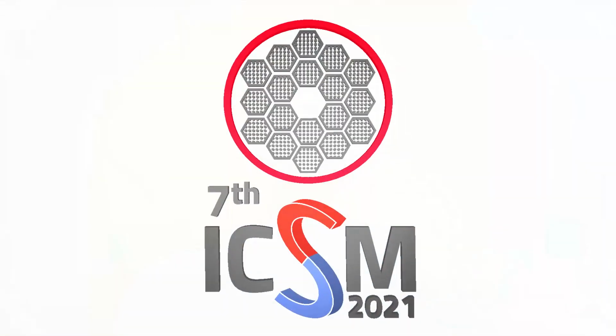They have very nice lattice matching between the superconducting matrix and themselves. Whereas with something like barium tin oxide, which are larger, he really can't put them in at very high densities because he does end up getting some strain that can affect TC. So with all of these, which I didn't mention, TC actually does not end up changing.